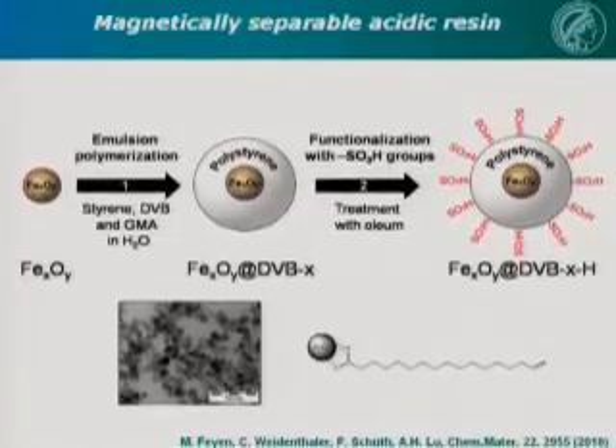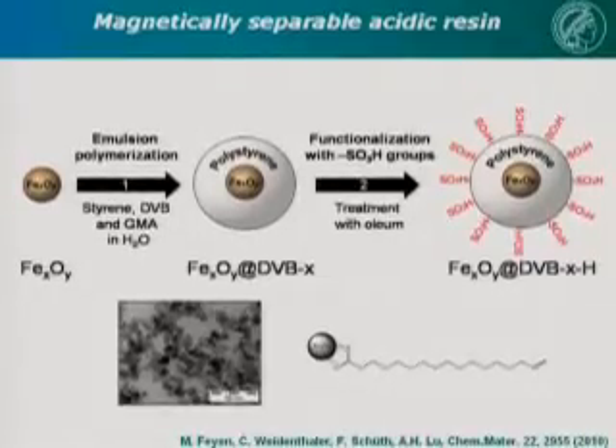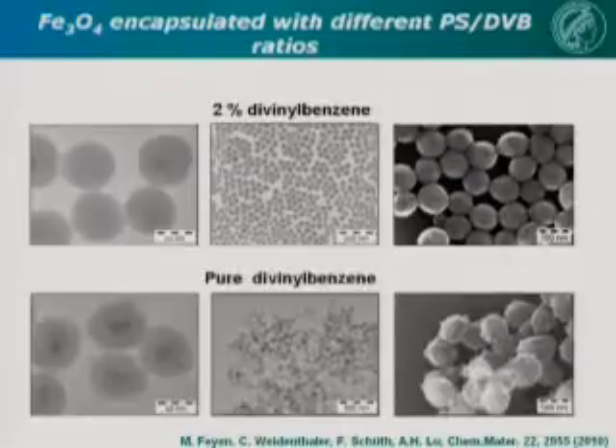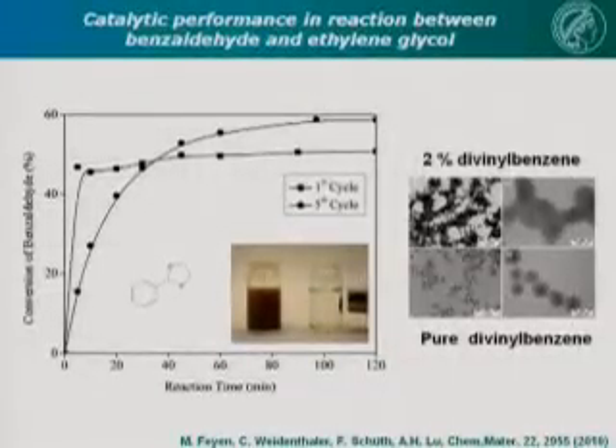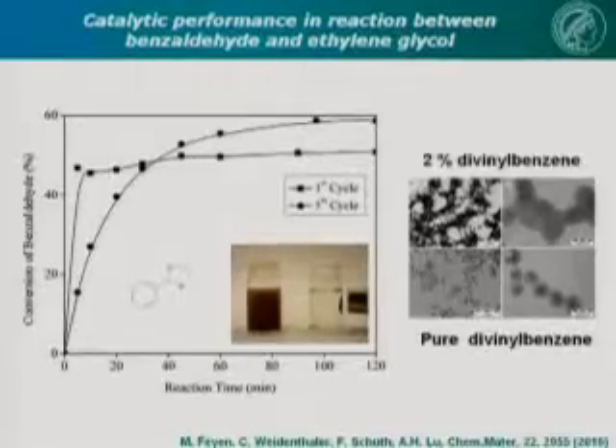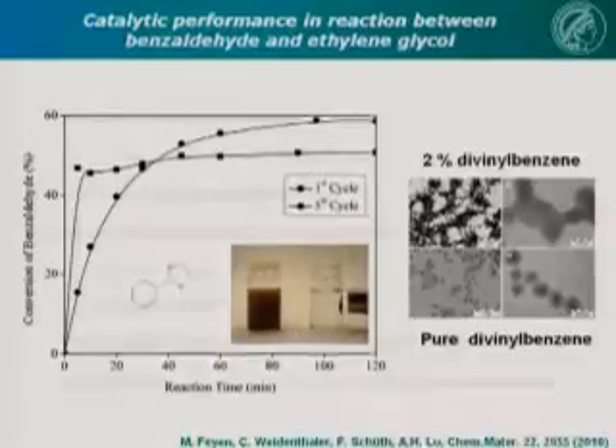And Matthias was the expert on making iron oxide nanoparticles. So he started with iron oxide nanoparticles, polymerized polystyrene or polystyrene divinylbenzene around it, and functionalized it with acidic groups by sulfuric acid or SO3 treatment, and then we basically had magnetically separable acidic catalysts, which were used here for the reaction between benzaldehyde and ethylene glycol to give this product. Magnetically separable, recyclable, well, it was not quite the same activity, but recyclable over several cycles by just magnetic separation and then decantation. So there are many opportunities for producing magnetically separable catalysts and getting an alternative to conventional separation methods.